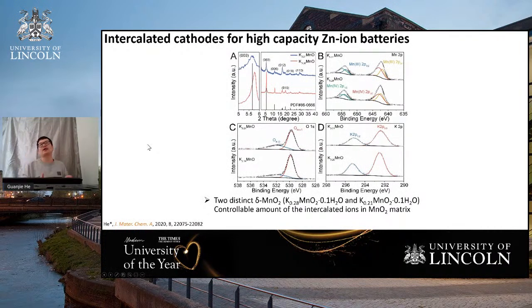And by using the wet chemistry synthetic method, we have successfully prepared controllable amounts of intercalated ions in the manganese oxide matrix. One is with potassium 0.28, and another one is 0.21. So for our traditional understanding, the one with less potassium ions might be more stable, right?